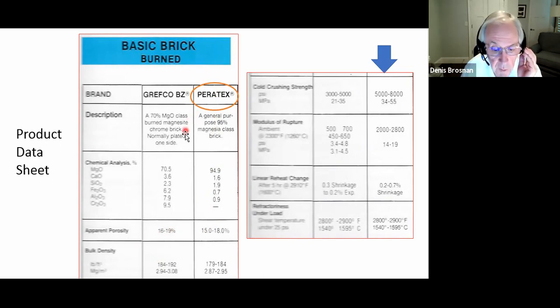You can see that there is a bulk density figure here given in both inch pound and metric units, and there is an apparent porosity figure given here, 15 to 18%. Now, this should be typical. It doesn't mean that every brick that was ever made called Peratex had less than 18% porosity. There were probably some that were under-fired, so to speak, and weren't mature, and maybe a little bit lower. But you should expect the average Peratex brick to be in the area of 15 to 18%.